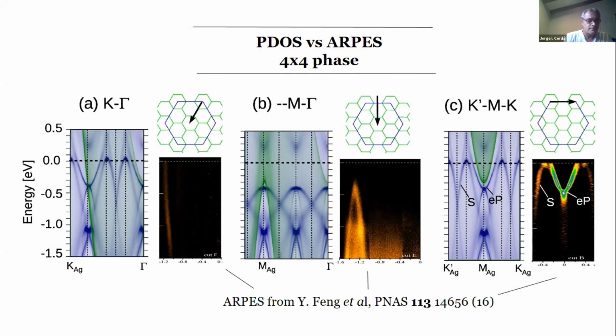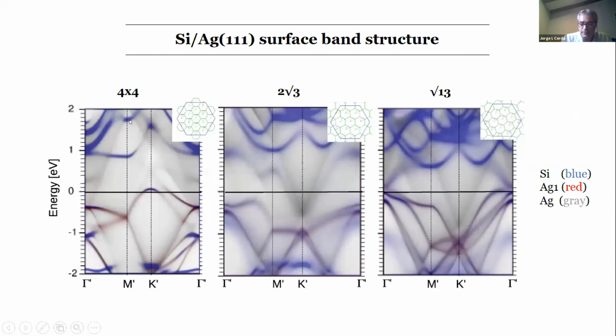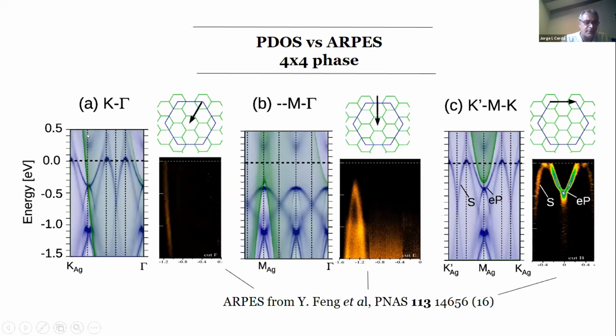What you see here is that along this direction, the only thing seen experimentally is this bright band here, and it actually coincides very nicely with the band edge of the bulk silver band. So it seems that they are really looking at the silver state, which probably has a photoemission signal much stronger than silicon.